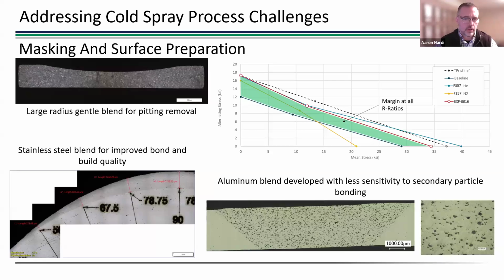You see the upper left image there. That's a large, gentle blend like you would use on most aerospace applications where you're trying to blend out pitting, porosity, things like that. And you can get very good fatigue performance when you do something like that with pretty much any material. So it could be your helium sprayed aluminum, like the examples I was showing before. There's no problem with pretty much any material when you spray into that gentle of a blend.